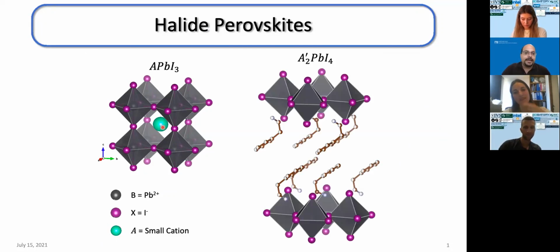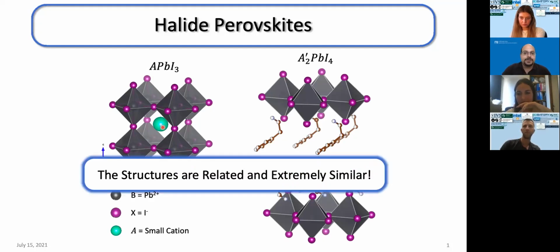Now, when the A cation is too big to fit the structure, it breaks the structure into a two-dimensional one, where we have layers of corner-sharing octahedra separated by a bilayer of the organic amine. Specifically, I'm going to focus on the lead iodine perovskites, where the inorganic layer is octahedra of lead iodine. Immediately from these structures, we can see that the structures of 3D and 2D perovskites are extremely related and extremely similar, which is our starting point.